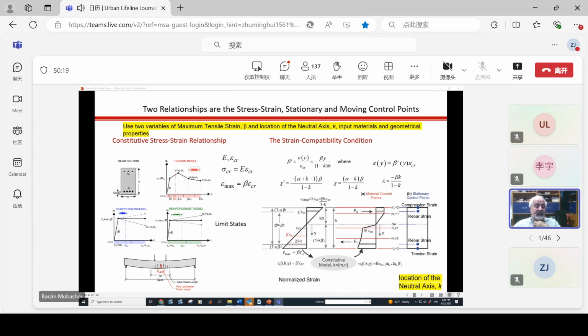So 4 pieces for tension, that gives me 4 segments, 2 zones for compression, and 2 zones for steel. So now I have a multiplication of 4 zones by 2 zones by 2 zones. And I have a strain distribution from my strain compatibility condition. And I have to use the geometry of the specimen that's defined in terms of here B and H, and also the location of the rebar. So all of these are variables that the designer can use, but they're all put in as a scalar. There is no dimensionality in this equation other than basically parameter E that is used. That's it. And everything else is non-dimensional.